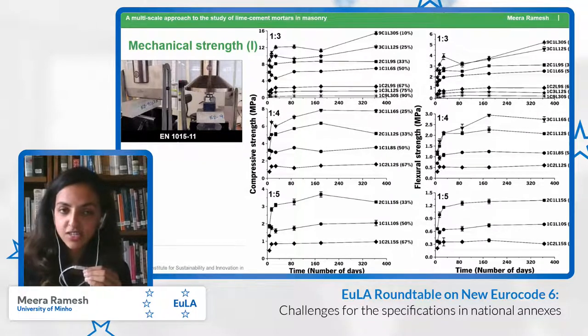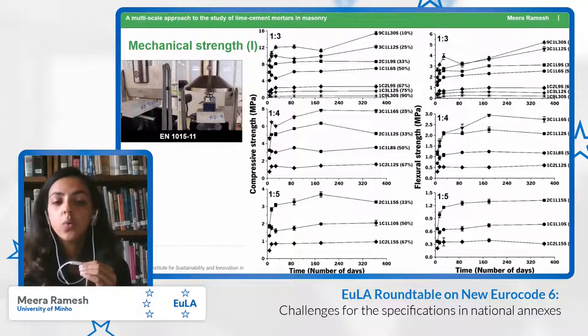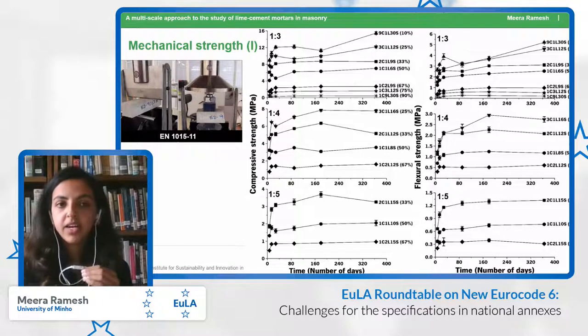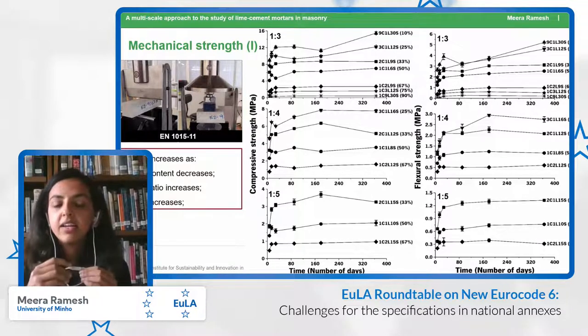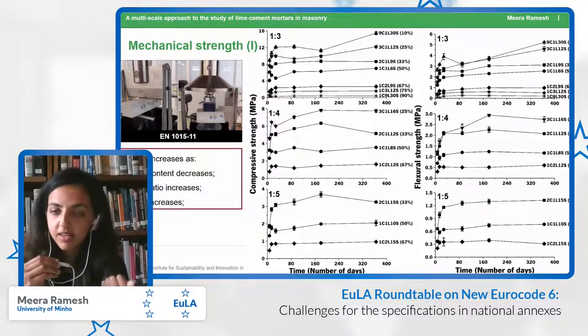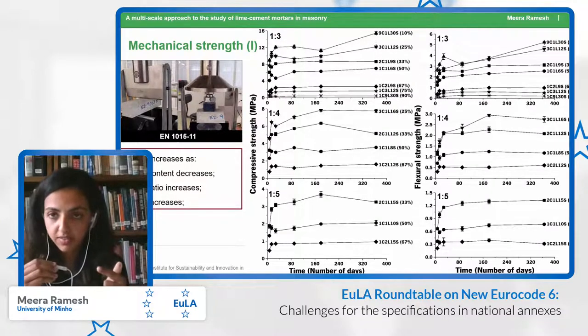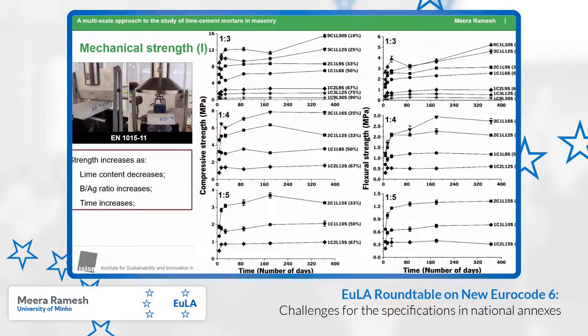So I'd like to draw your attention to the fact that on the y-axis, we have mechanical strength in megapascal, and on the x-axis, we have time in number of days. And the takeaway from this slide is that, A, strength of the mix increases as the amount of lime in the binder decreases. B, as we increase the binder aggregate ratio, the strength of the mix increases. And finally, for every single mix, even though there were ups and downs, over a period of time, the strength increased and then it tended to stabilize.